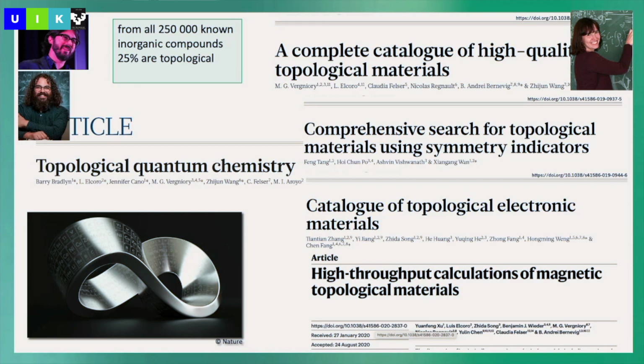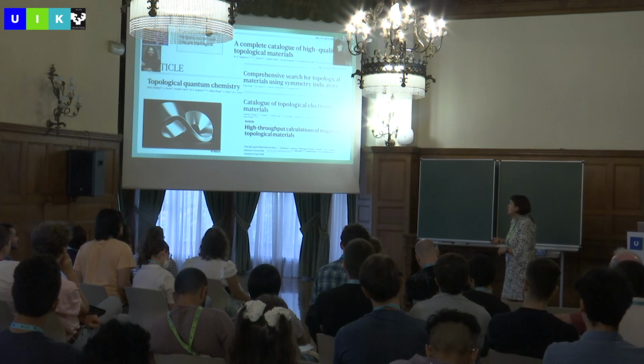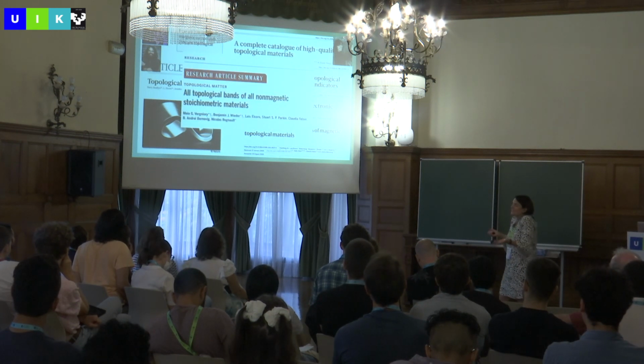And this is nice for all the people now working on topology, because based on this database, you can now do band structure calculation, the single particle pictures, and you make all your treatment, and then you can learn that from all the 250,000 compounds which we know, at this time around 25% is topological, and we are even looking now for magnetic materials which are topological, but now it's more or less everything is topological.